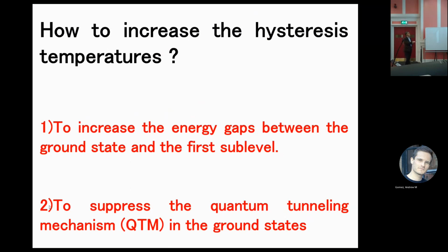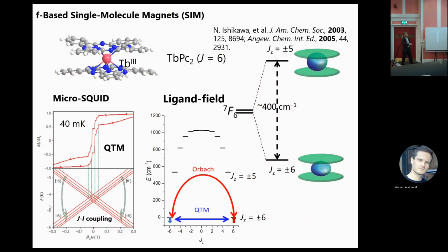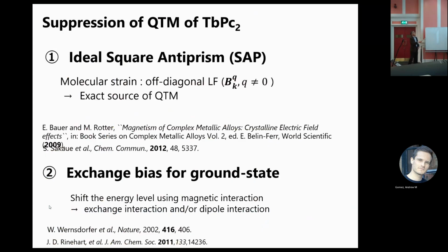So, two important things: to increase the energy gap between the ground state and the first excited state, and to suppress the quantum tunneling mechanism, QTM, in the ground state. Both are very important to increase the hysteresis temperature. If the potential barrier is very high, but quantum tunneling occurs at the ground state, the hysteresis temperature is very low. So we must suppress the quantum tunneling at the ground state.